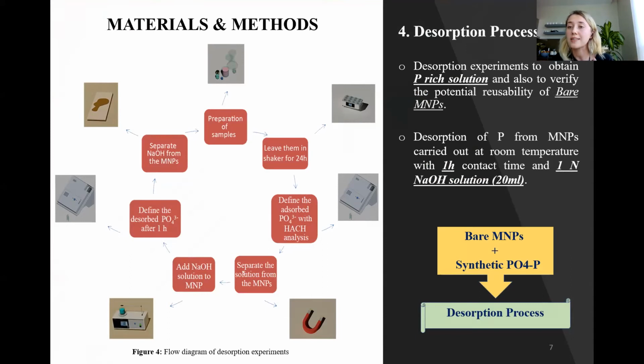Sodium hydroxide solution is actually the most effective on phosphate from magnetic iron oxides. So this was attributed in many studies in the literature actually. Especially the study of Dow et al. that I just mentioned in this slide, they dissolved the phosphate ions by sodium hydroxide solutions. However, this kind of experiments, I mean the desorption processes, are generally provided by basic solutions, we can say. Okay, based on literature.